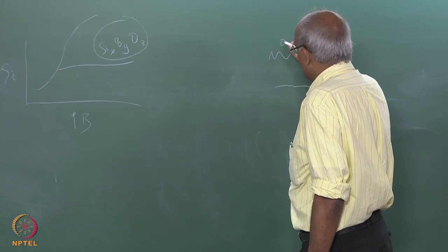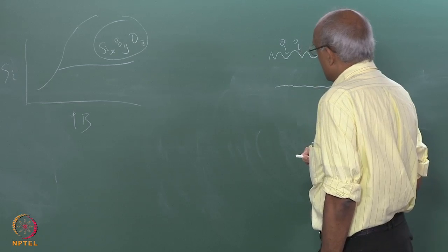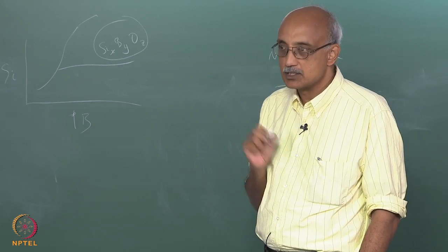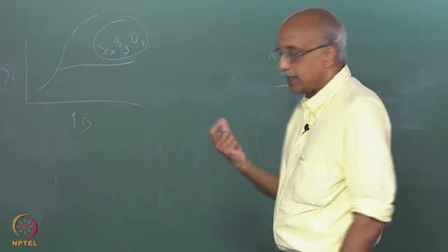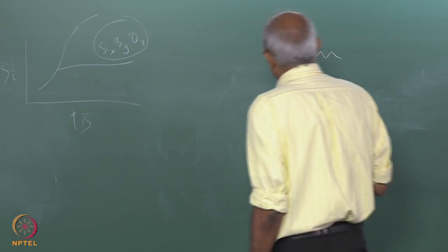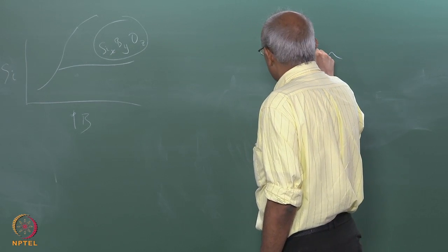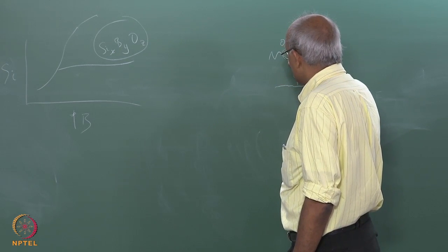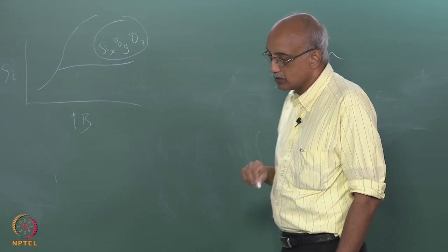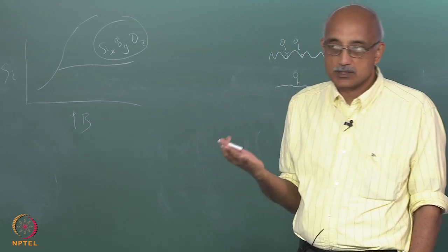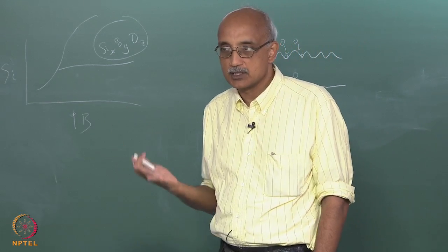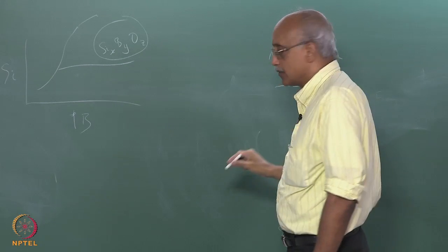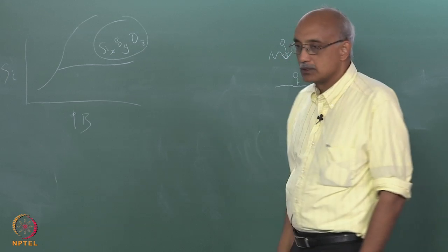When an arriving molecule sees this surface versus this surface, the effect of surface roughness on capture efficiency or sticking probability is different, depending on the scale of the roughness that is present on the surface. For example, if the roughness asperities are larger than the arriving molecule diameter, then it's fairly easy for the arriving molecules to get captured on the surface. So a rough surface will actually increase the sticking probability in such cases, primarily because it now provides a larger surface area for capturing the oncoming molecules compared to the smooth surface.